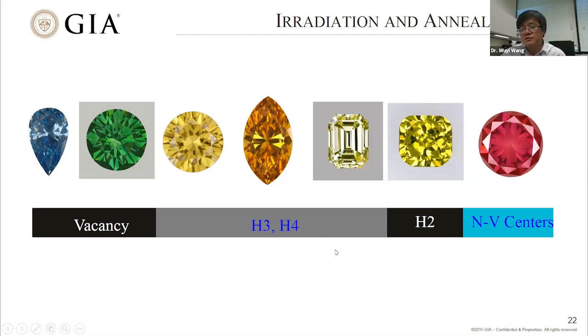And for a small group of stones, if heated to a very high temperature, a high concentration of H2 defect could be introduced that could create another type of green, but not as bright a green compared with the green due to H3 fluorescence. If a natural diamond has a little bit of isolated nitrogen, and this stone is irradiated and annealed, NV centers will be introduced. That will turn the stone pink or red, depending on the concentration of isolated nitrogen and also the treatment conditions. I just want to point out that natural diamond with a suitable concentration of isolated nitrogen is very, very rare. So natural material suitable for turning pink is not so easy to find.